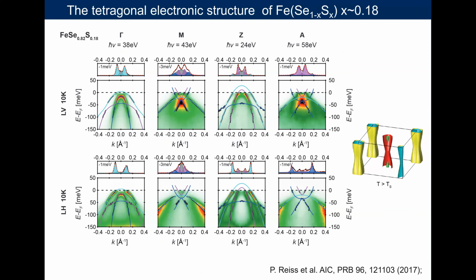So when we look at the data, I just want to show you that in our experiments, when we measure the spectrum, we have to be aware that different light polarization affects the intensity of the different bands. This is because we have the dxy bands and the dxz bands, and the way the intensity changes is because of the matrix element between the light polarization and the orbital character of the bands.